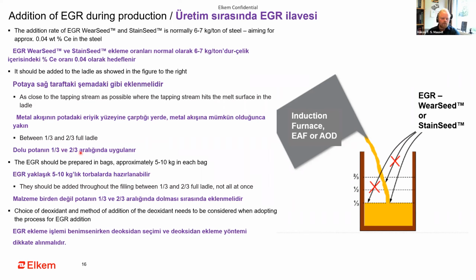The alloy should be packed in bags, paper bags or plastic bags, between 5 to 10 kilograms in each bag. And then you should try to add it as evenly as possible between 1/3 and 2/3 filled ladle. So you have to distribute the EGR during the filling.